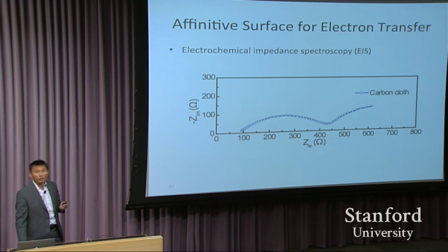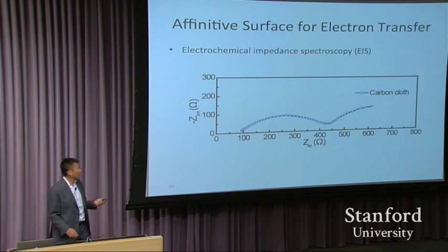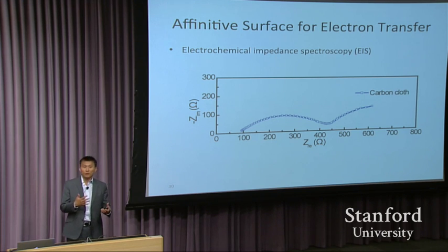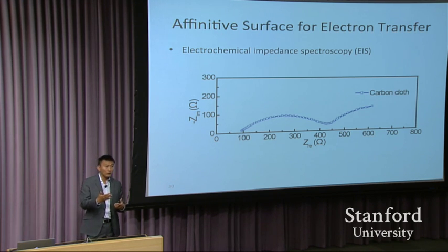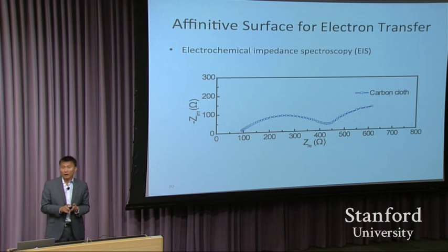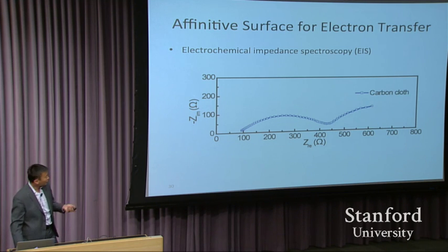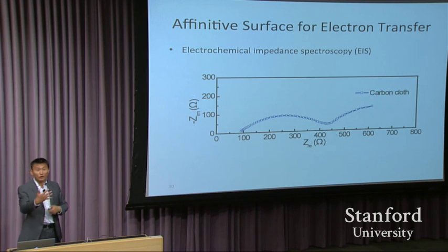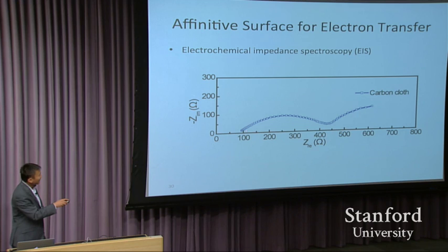So this also shows us so-called impedance. We can use AC impedance, using alternate current or voltage, to measure the charge transfer impedance between these microbes and your electrodes. So this is the one using carbon cloth. This is a semicircle. Without teaching you how to read this curve, you have to believe me. That's how you read it.